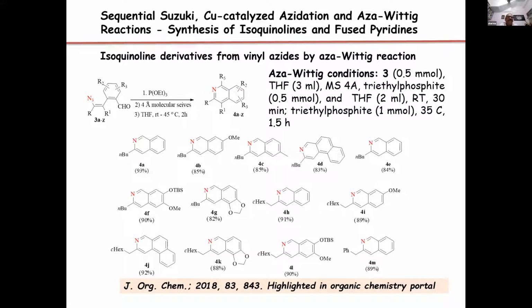Then the thus prepared vinyl azides were subjected to a reaction with triethyl phosphite in THF at room temperature for 30 minutes. Then after the evolution of nitrogen, one more mole of triethyl phosphite was added and heated at around 35-40 degrees for an additional 1.5 hours to get the isoquinoline systems in excellent yields. Next, please.